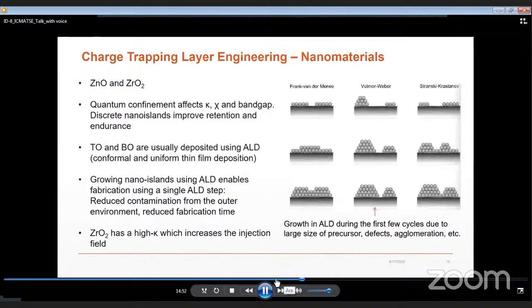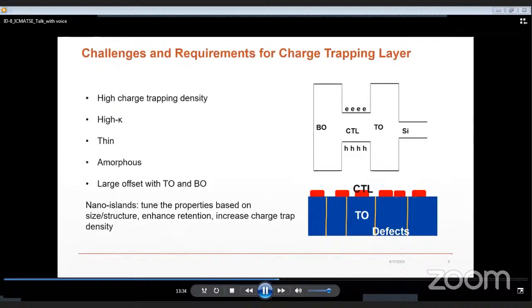As for the tunnel oxide, the charge trapping layer is preferred to be amorphous in order to reduce the charge leakage probability. Also, this layer should have a large band offset with the tunnel oxide and blocking oxides in order to better confine the stored charges and therefore improve the charge retention characteristic of the memory.